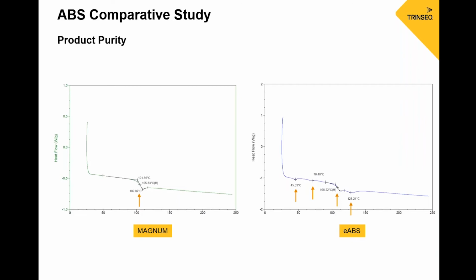So we're going to talk about the product purity, and this information was gathered using a DSC, differential scanning calorimeter. And you can see on the left, the mass ABS, the Magnum 3904, where we see one transition, one thermal instance, where the glass transition is. So around 109C for the glass transition, or 105 at the midpoint. And that's the only thermal instance that we see. In the emulsion product, we see several instances that result from the residuals and additives that are in the product. These could be low molecular weight additives for processing, and could also be something that's specific to the performance of this product also. But there are a lot of other things present, is the main point of this from a purity standpoint.